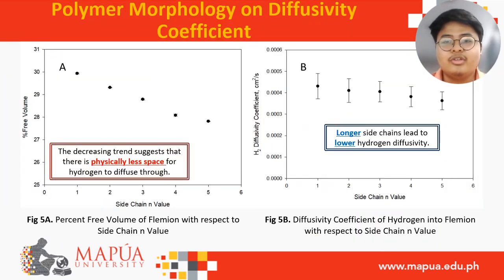In relation to polymer morphology, we have determined the hydrogen diffusion coefficients. This is seen in figure 5b, where we can see that longer side chains lead to lower hydrogen diffusivity. Now, in order to better understand this, we also calculated the free volume, which is seen here in figure 5a, where the decreasing trend suggests that there is physically less space for hydrogen to diffuse through. The lower free volume relative to the unit cell volume suggests that there is physically less space for hydrogen to diffuse through. This means that a low percent free volume translates to less hydrogen diffusion, which reflects in hydrogen having low diffusivity coefficients in Flemion as summarized in figure 5b.